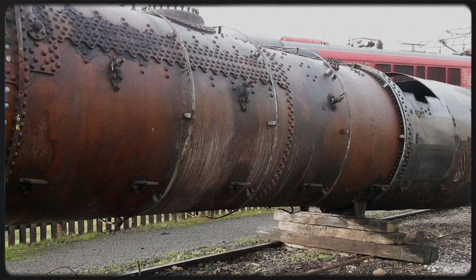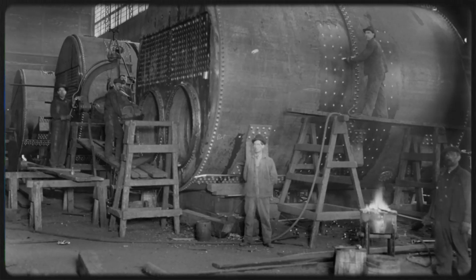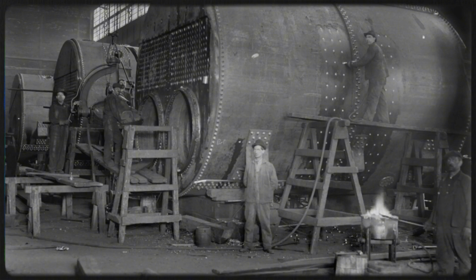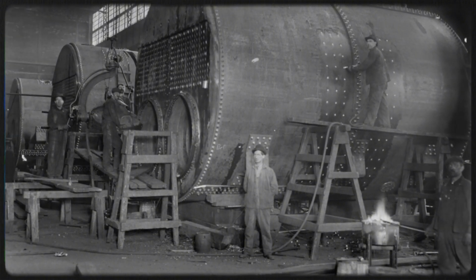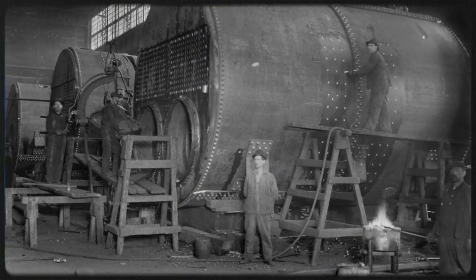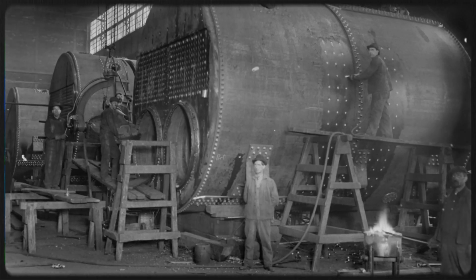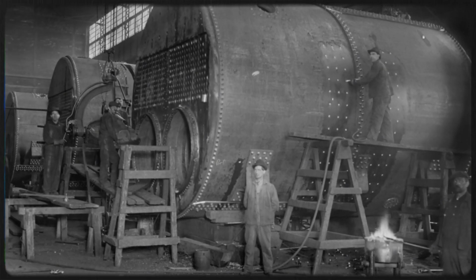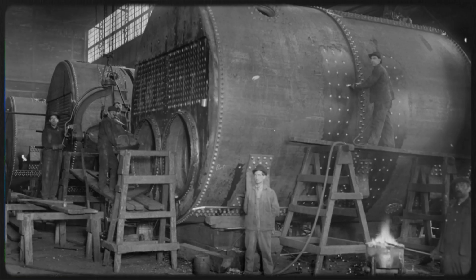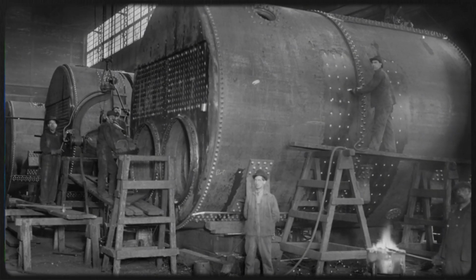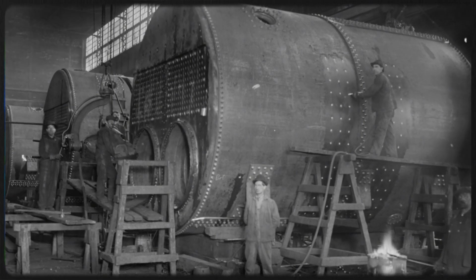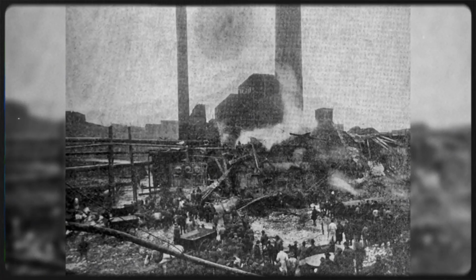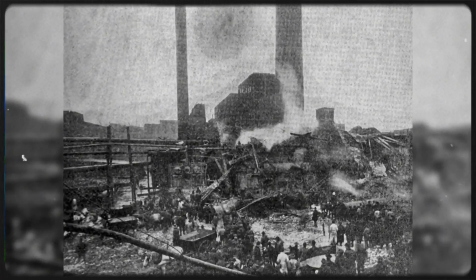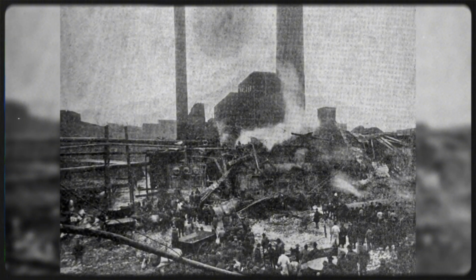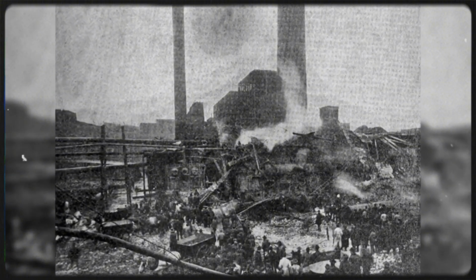The interaction between these different failure modes made boiler safety particularly difficult to manage. A boiler might be operating within its pressure rating, but if its walls had thinned due to corrosion, that rating was no longer valid. A boiler might have perfectly good water level indicators, but if the indicators were coated with scale and giving false readings, the operators were essentially flying blind. Problems compounded each other in ways that were difficult to anticipate and almost impossible to detect without systematic, rigorous inspection.